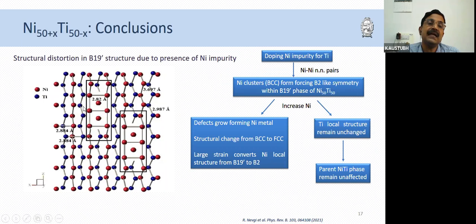So what it means is, if I can make a schematic of this nickel titanium doped with nickel, then you have this B19 prime structure, and within this B19 prime structure, because you have doped excess nickel, you start getting these kind of body-centered cubic nickel defects. And this defect forces a B2-like symmetry, because it is body-centered cubic, and that produces a strain. So what we said was, doping nickel in nickel titanium will produce nickel-nickel nearest neighbor pairs, and that will form body-centered clusters of nickel, which will force B2-like symmetry within the B19 prime phase of nickel 50 titanium 50.